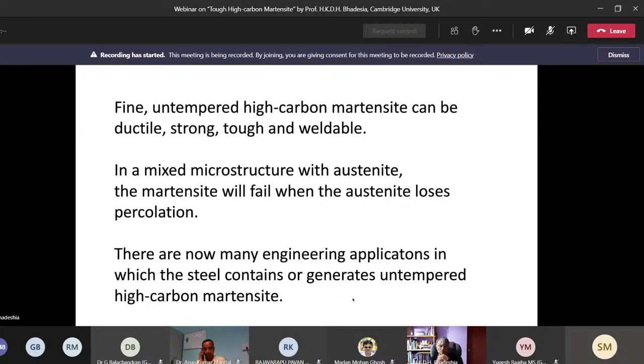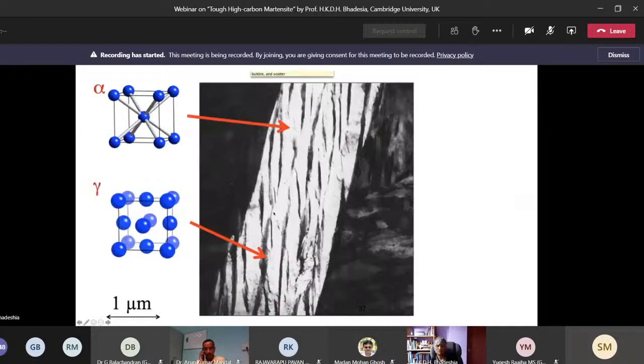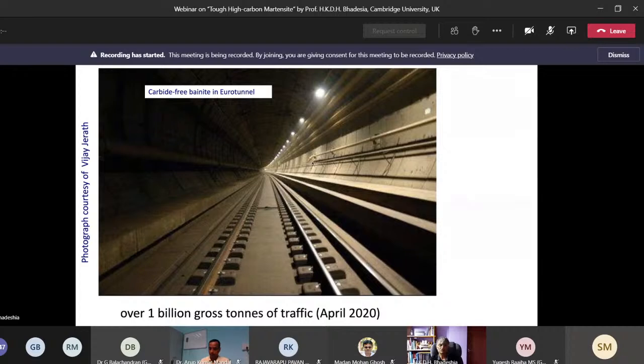In a microstructure where we have a mixture of bainitic ferrite and austenite to start with, this austenite under the influence of service will, near the surface, tend to decompose into high carbon untempered martensite. And I'm talking here about the first ever carbide-free bainitic rail, which was installed inside the Channel Tunnel connecting England and France many years ago. In April 2020, I was sent a message that 1 billion gross tons of traffic have gone over the rail without any need for grinding.